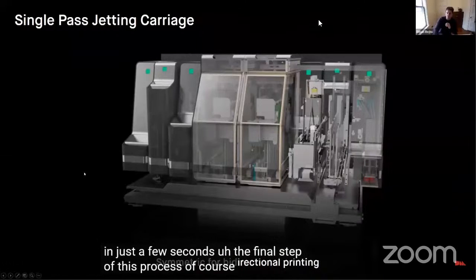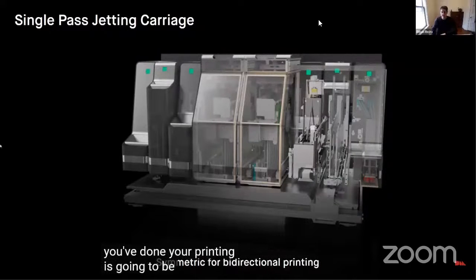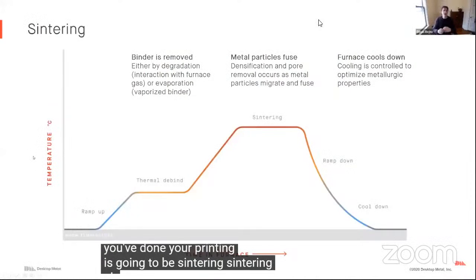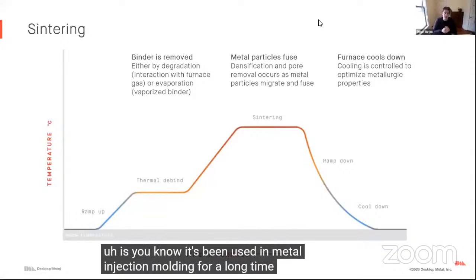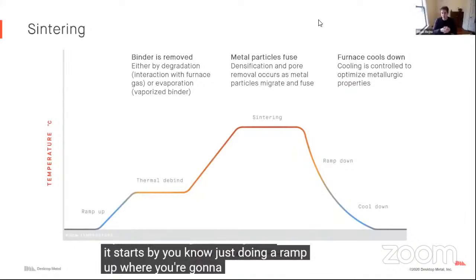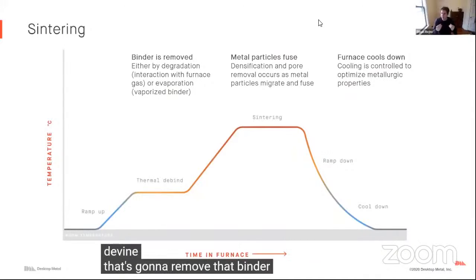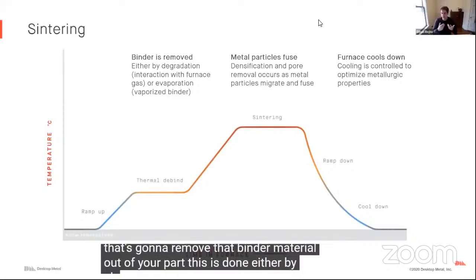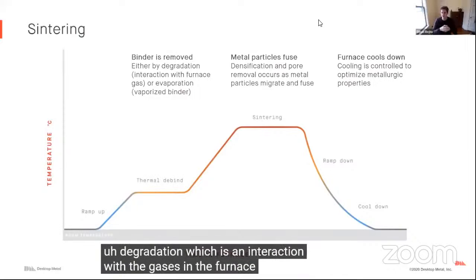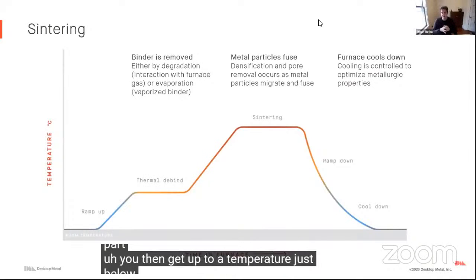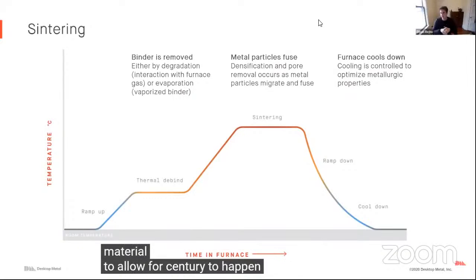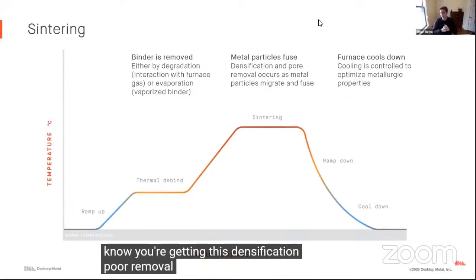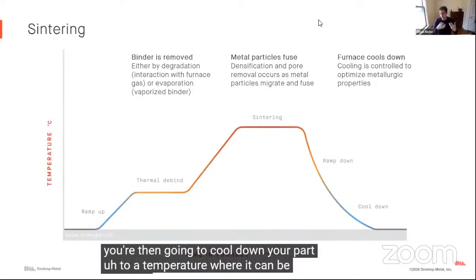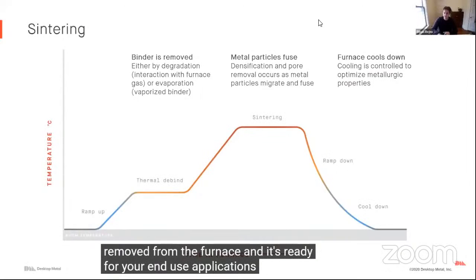The final step of this process, after you've done your printing, is going to be sintering. Sintering has been used in metal injection molding for a long time. It starts by doing a ramp up where you're going to do your thermal debind. That's going to remove the binder material out of your part. This is done either by degradation, which is an interaction with the gases in the furnace, or by evaporation, where you're literally just boiling your binder out of your part. You then get up to a temperature just below the melting temperature of the material to allow for sintering to happen, where you're getting this densification, pore removal. We're getting densities above 99%. You're then going to cool down your part to a temperature where it can be removed from the furnace and it's ready for your end use applications.